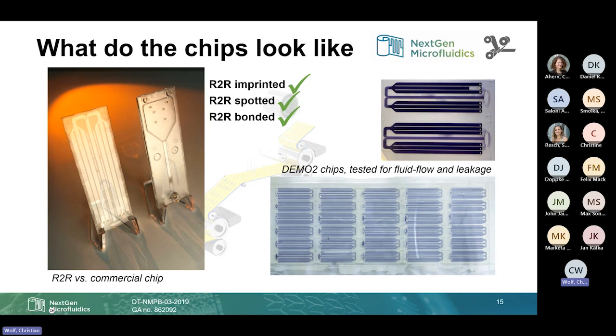What we also did here is a thorough testing of the chips concerning fluid flow, leakage, and so on. And after the optimization of all processes, only very minor leakages and samples not working concerning fluid flow could be observed. Typically this is already done before singulation in these tests, because there's no need to singulate the chips by laser cutting beforehand.